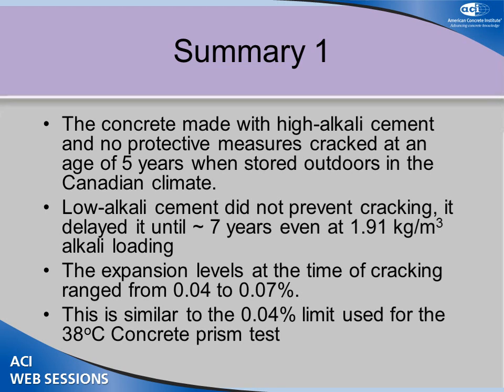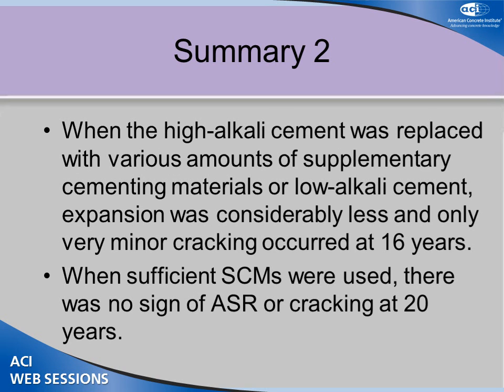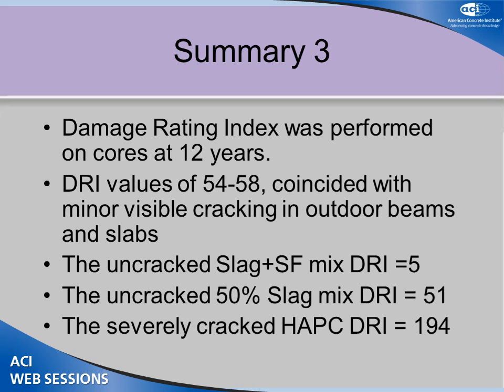The cracking we saw was in the order of 0.04 to 0.07, which is just above what we use for the concrete prism test limits. When we used enough supplementary cementing materials or low-alkali cement, we reduced the expansion relative to the high-alkali cement, as you might expect. And when we used sufficient SCMs, there was no sign after 20 years of ASR cracking or expansion. The damage rating index sort of tied into the relative amounts of damage we saw, although we'd like to do some more of it to see if it's progressing.